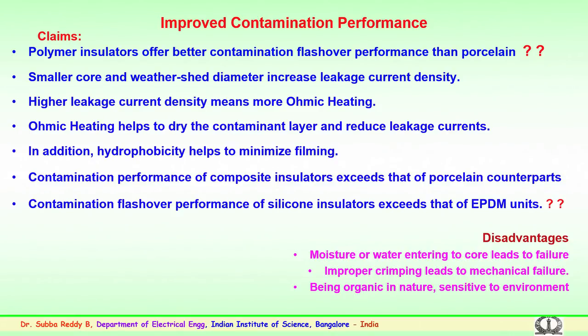This ohmic heating helps to dry the contaminated layer and reduce the leakage currents. The reason is, once the polluted layer formed on the insulator surface becomes wet, conduction happens, the surface gets conducting and the leakage current flows. Because of the heating, with lesser surface area compared to ceramic, the heating here is more. This helps to dry the contaminated surface. Further, once the surface dries, the dry band, or the formation of the dry area, offers a very high resistance, and that reduces the leakage current flow. This is one of the major advantages, because of the hydrophobic nature, the water-repelling property of the polymer insulator, which is an advantage compared to the earlier ceramic or porcelain insulators.